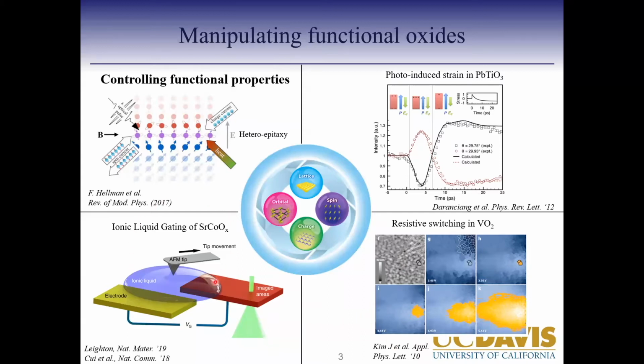And even in materials like strontium cobalt oxide, you can use an AFM conducting tip to cause transformation between 2 different crystal structure phases. And some of these transitions you can cause at very, very fast timescales, which is an interesting avenue for devices, moving away from the traditional way of controlling the material, and utilizing lasers to control these systems. So here you can change strain in lead titanate at the timescales of picoseconds and transform the crystal structure from more tetragonal towards cubic.